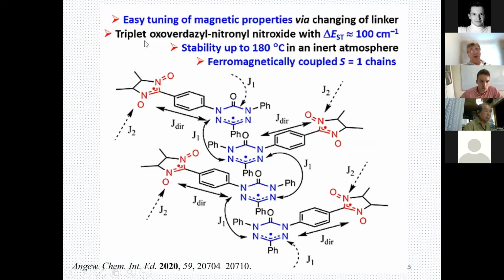we can now combine a bridge between two radical groups, and use an appropriate connection between this bridge and the oxo-verdazyl molecule. We can easily tune the magnetic properties of the oxo-verdazyl-nitronyl nitroxide radical. Also, we revealed a triplet oxo-verdazyl-nitronyl nitroxide with a very large triplet-singlet energy gap, more than 100 inverse centimeters. All molecules have very high stability.